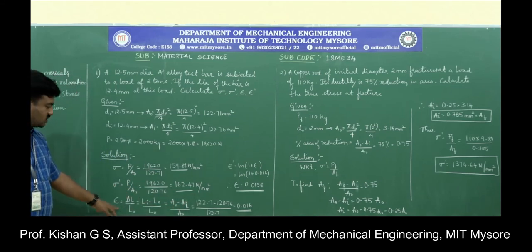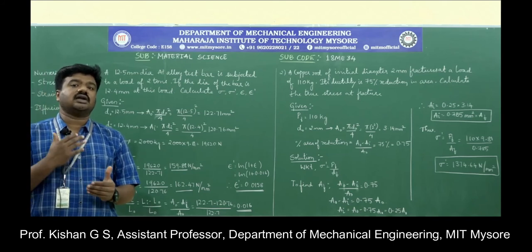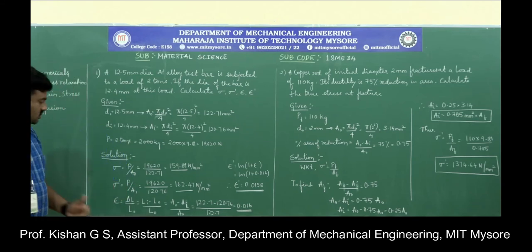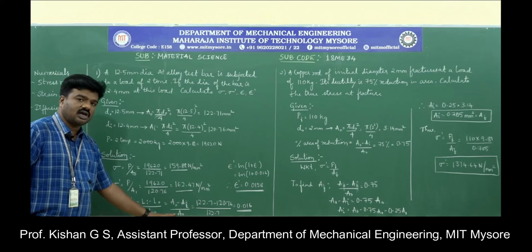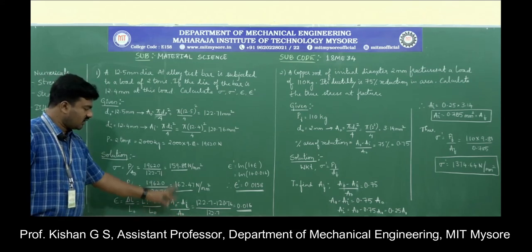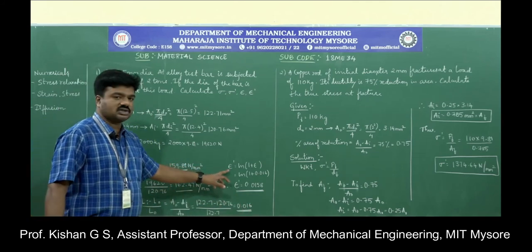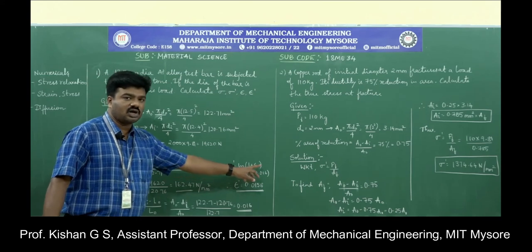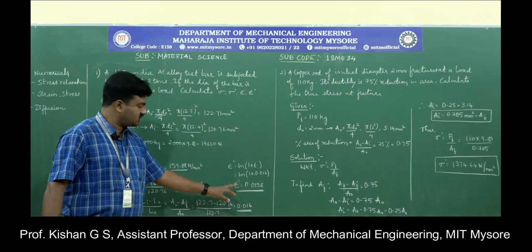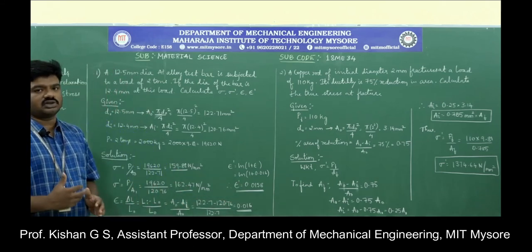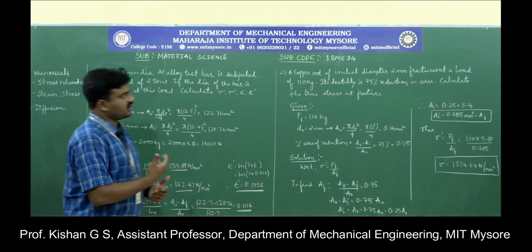Since no length values are given, engineering strain is calculated using area: epsilon = (A₀ - Ai)/A₀ = 0.016. True strain epsilon' = ln(1 + epsilon) = ln(1 + 0.016) = 0.0158. It is direct substitution; the key is to convert load into Newtons and substitute the correct area values.